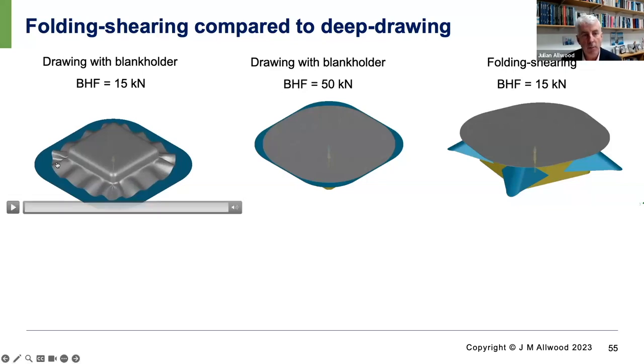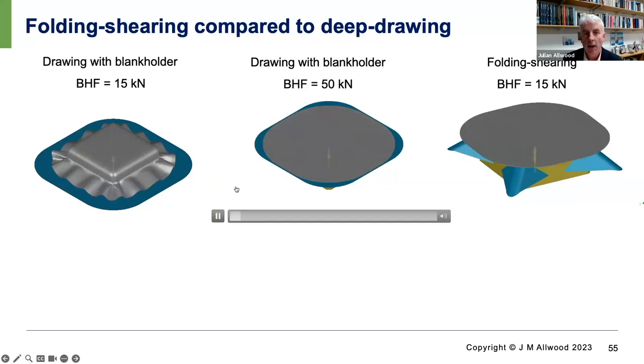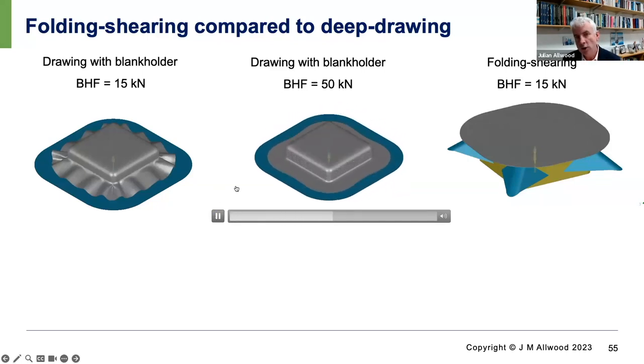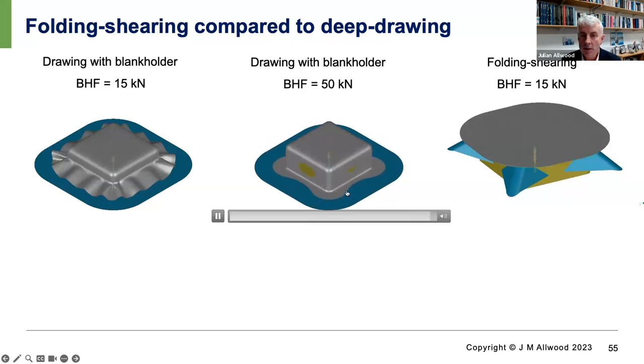If you have a blank holder without enough grip, then you end up with wrinkling. If you grip it correctly, then you can draw the whole part. But you can see at the bottom, you've got quite a lot of material that you're going to trim off. And this amount of material grows and increases as the part becomes more complex.